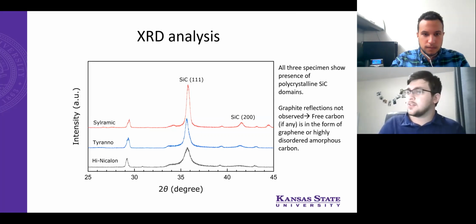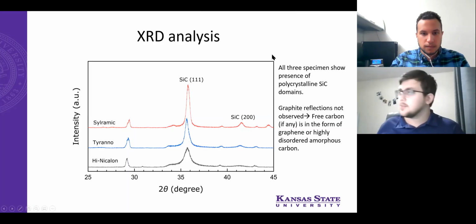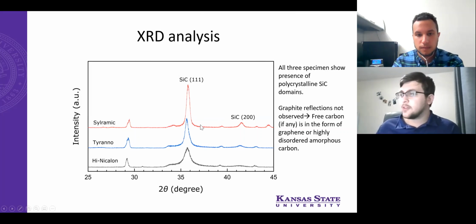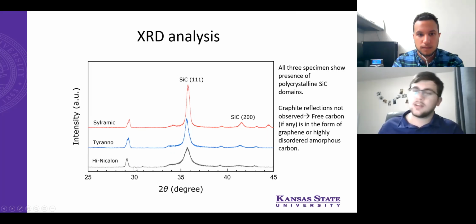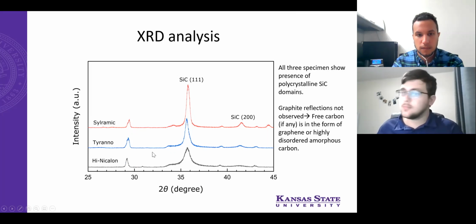Here's the XRD analysis, or the X-ray diffraction, I believe, that Dr. Singh did. So all three of them showed a presence of polycrystalline silicon carbide domains. They're all very similar ultimately. And Dr. Singh believes this left peak over here is likely carbon. And then we can see that the Hi-Nicalon seems to have a less ordered silicon carbide domain, just based on how wide this is. And then the Sylramic seemed very ordered just because of how thin and high this peak is.